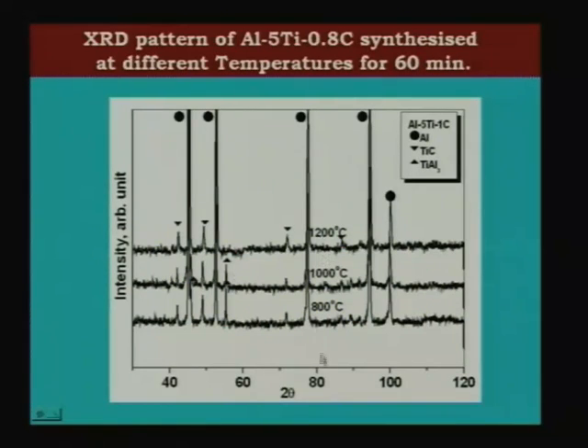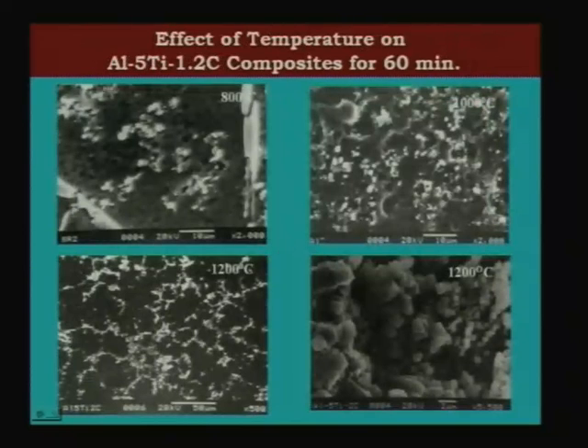Here you can see different temperatures, the formation of both TiAl3 and TiC can be seen here, and this is with 1.2% carbon. In 1.2% carbon you can see that only TiC forms. How do you know that these are only TiC? One can do an X-ray of them, one can extract these particles and then study the X-ray of those particles, or one can do EDAX on those individual particles and find out whether they are TiC particles or TiAl3 particles. If they are TiAl3 particles, you can easily see in the EDAX that there will be no carbon peak coming out of those particles. One can easily say, yes, these are not TiC particles.